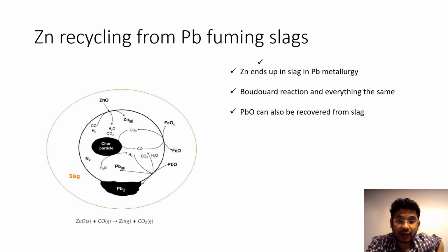You can also recover lead oxide from this slag in a different manner, but everything else is pretty much exactly the same. First you have the reduction reaction, then the zinc vapor escaping, then combustion, and then formation of zinc oxide. So that's one thing. It's not done in a Waelz kiln or something. They do it in a separate type of furnace, but the principle remains almost the same.